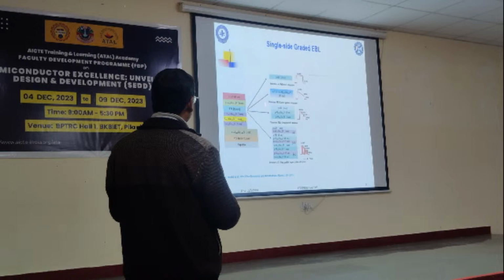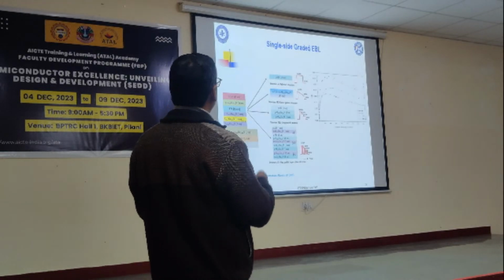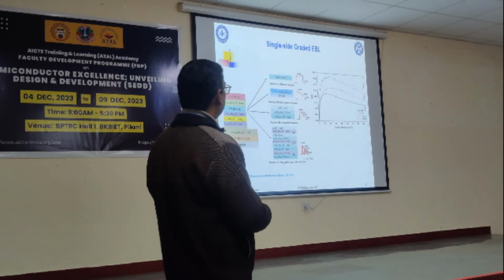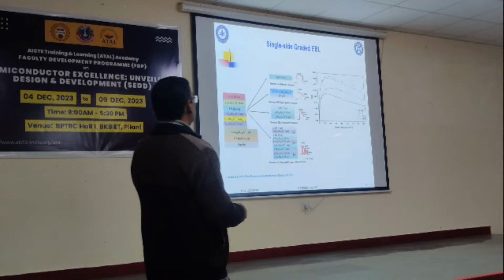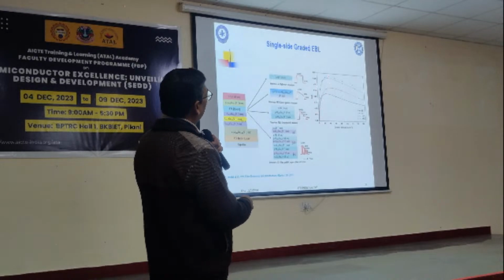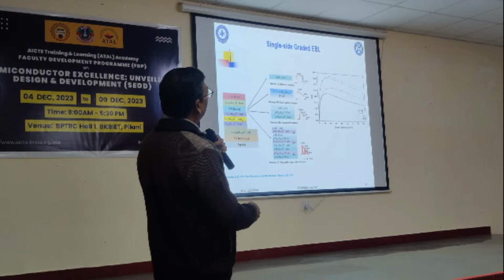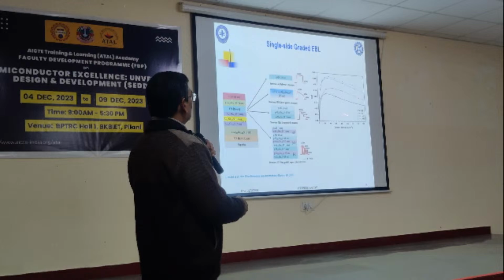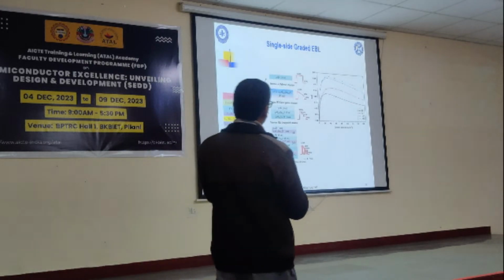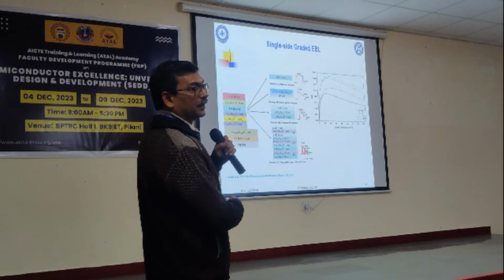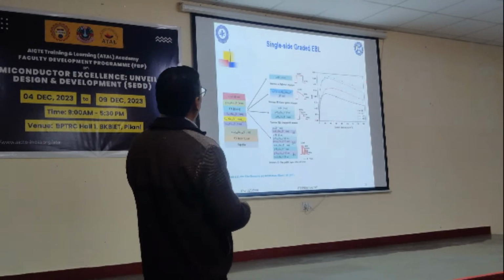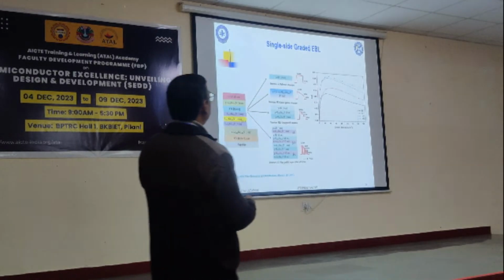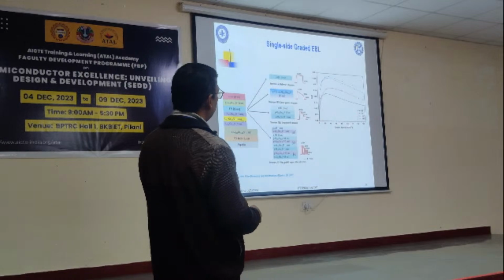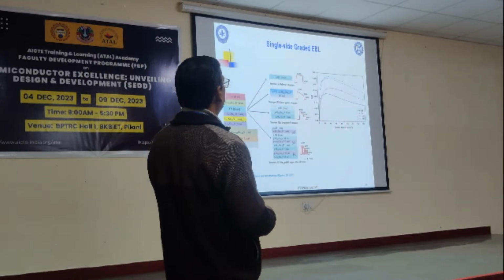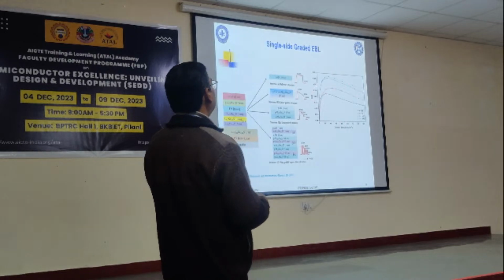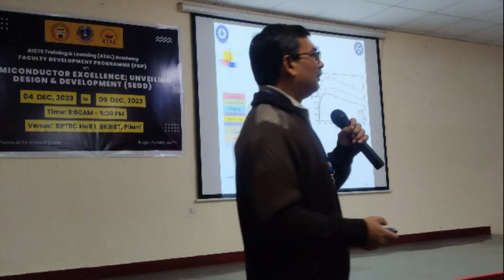So here are a few designs for how we can minimize the droop. What I call droop is that as the current density increases, the internal quantum efficiency increases, but after a certain level, it then decreases. It should not happen, but that happens due to this polarization property. How to minimize that? Because what we need is high light output power. So we need to operate at higher current, but when operating at higher current, the efficiency will go down. So although we will get a little bit higher light output, the efficiency is less.